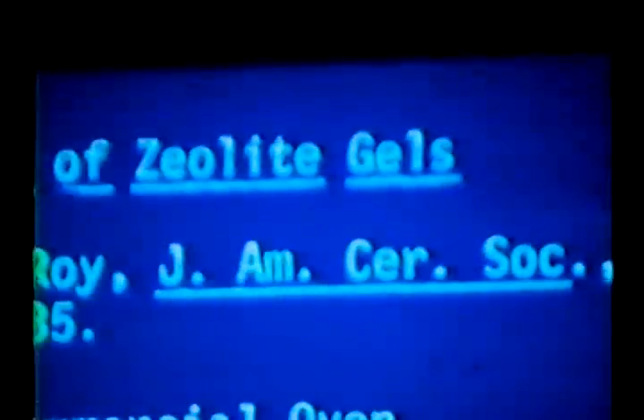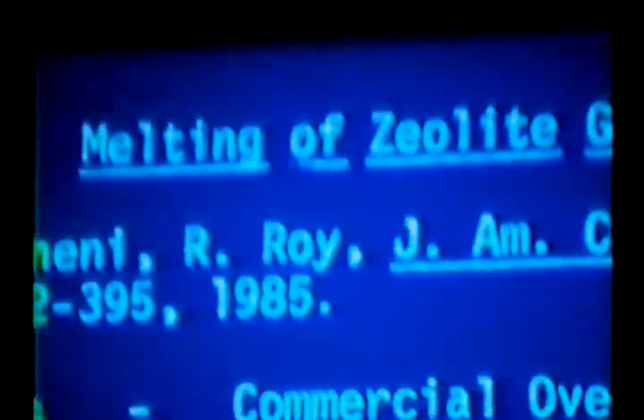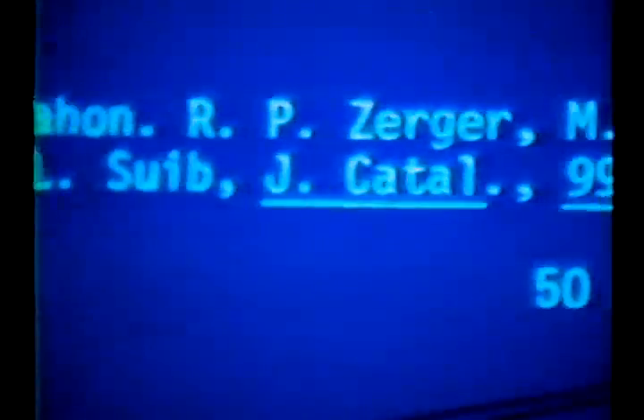Now, when I present this work, especially to oil companies, Exxon, Mobil, places like this, people say, "Gee, just like cooking a chicken. You're just heating it up." Oh, I want to make one real important point here. People have done that. Rustum Roy has done this, where he's used a commercial microwave oven of 600 watts and melted zeolites. His object was to make sols and gels for ceramic purposes. What we're doing, published in Journal of Catalysis in '86, is using 0 to 5 watts. We're controlling that power and keeping it as low as possible. And what we think we're doing is selectively breaking the metal carbon bonds so that carbon monoxide leaves. If we use 50 watts, we find that the zeolite melts. You can see aluminum metal in an X-ray powder pattern. So I think one of the keys to using this method for making small metal particles is to use very low power.